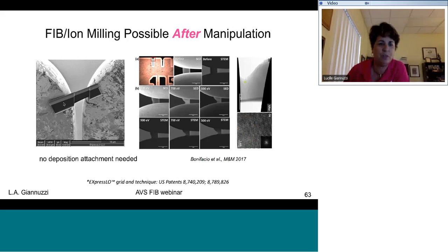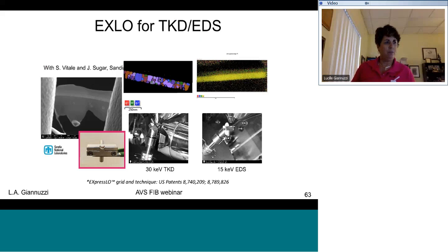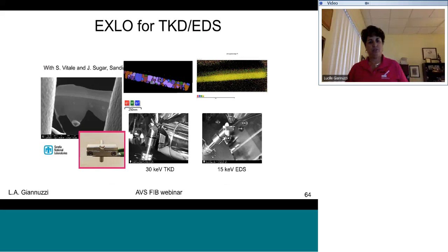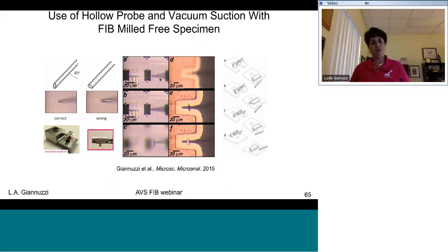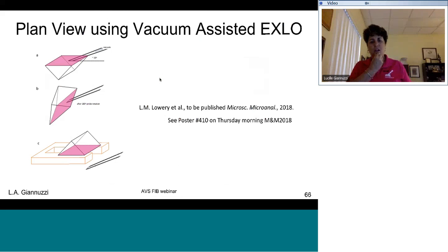You can FIB mill the sample after the sample is already on the grid without any additional deposition, either with FIB or with an argon ion mill, such as a nano mill or pico mill. So you can do your low energy polishing as well. You can use it for transmission Kikuchi diffraction or EDS or whatever, using different geometries. You can also pull vacuum through a hollow probe, and this double hollow probe to optimize collection angles.